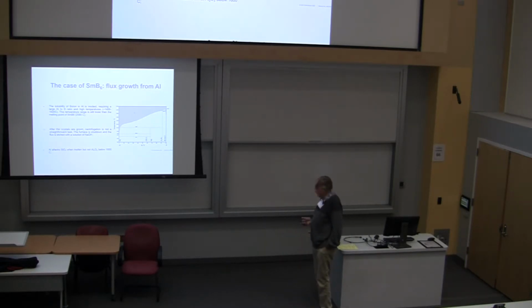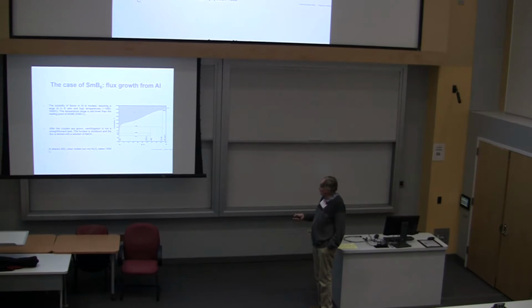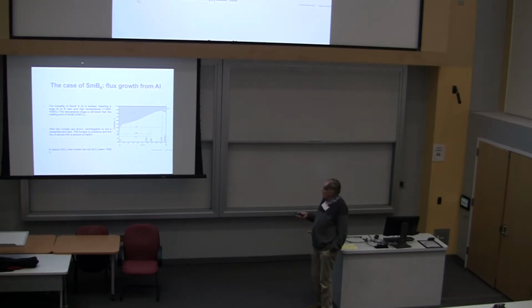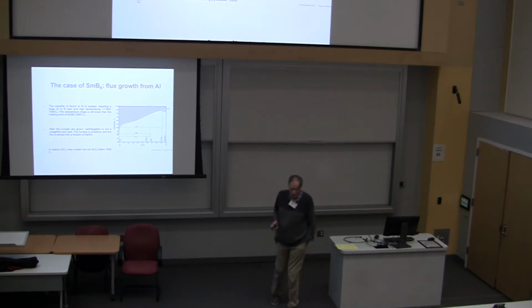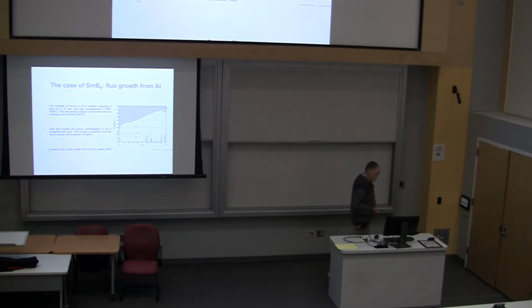Okay, so let me talk about, for instance, this interesting material that we're going to have a workshop on tomorrow, samarium hexaboride. The hexaborides are a beautiful, really simple cubic crystal structure, which actually you can grow from aluminum. But you can see, for instance, here's a phase diagram of aluminum and boron. And you can see that the solubility of boron in liquid aluminum is actually quite low. It also turns out that these rare earth hexaborides are extremely stable compounds. And the more stable, or as they say, more refractory a compound is, usually the lower its solubility.